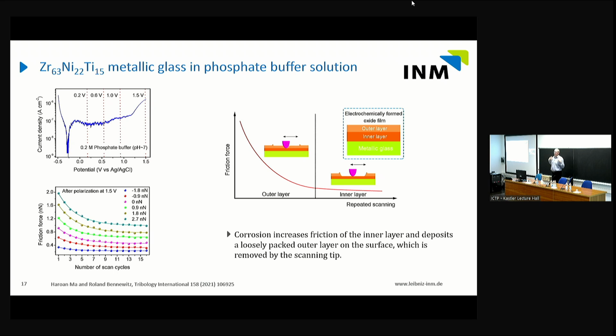It's not our word, it's the word of the corrosion community, the inner layer and the outer layer. The inner layer is something like 1.5 nanometers. The outer layer is usually unknown because its density is low, and this outer layer we can simply move away with an AFM tip. And that's what's happening here essentially. This decrease in friction force is because we need extra friction force to remove the layer, but once it's gone, we actually have a stable system.